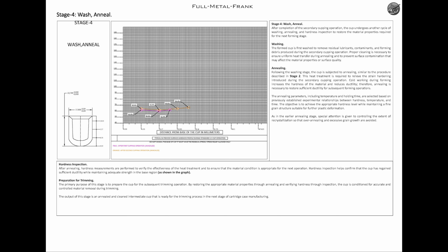The annealing parameters, including temperature and holding time, are selected based on previously established experimental relationships between hardness, temperature, and time. The objective is to achieve the appropriate hardness level while maintaining a fine-grained structure suitable for further plastic deformation. As in the earlier annealing stage, special attention is given to controlling the extent of recrystallization so that over-annealing and excessive grain growth are avoided.